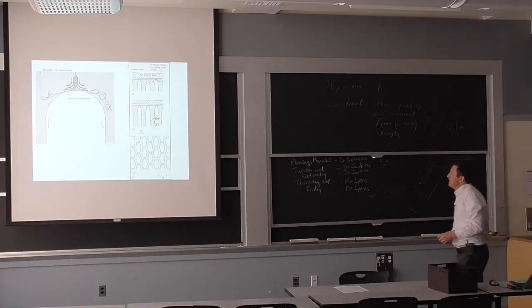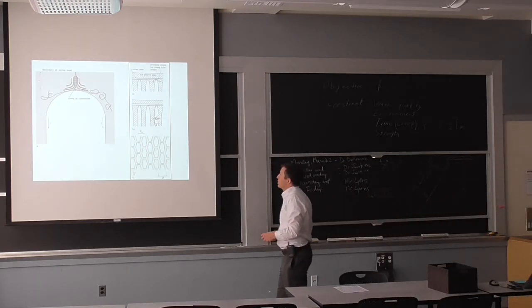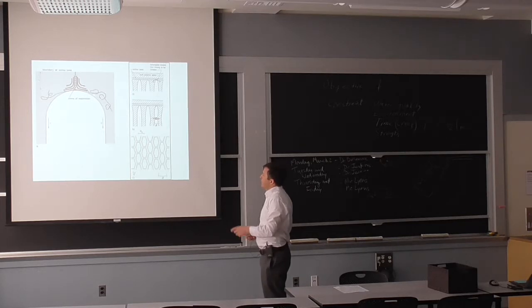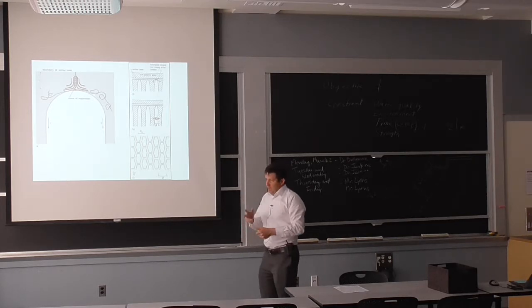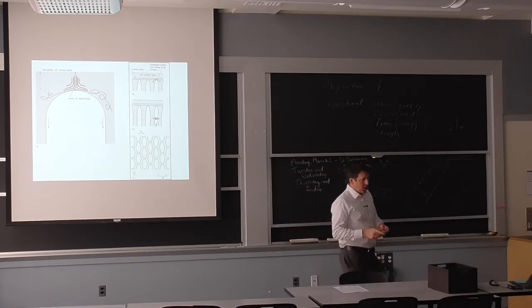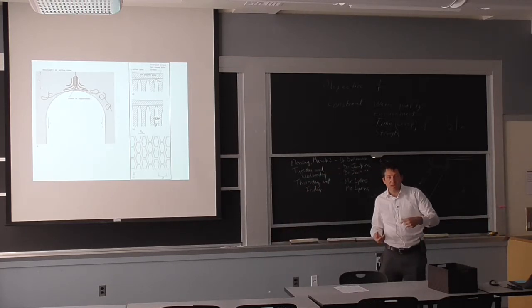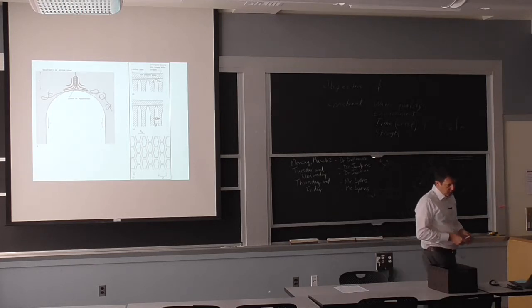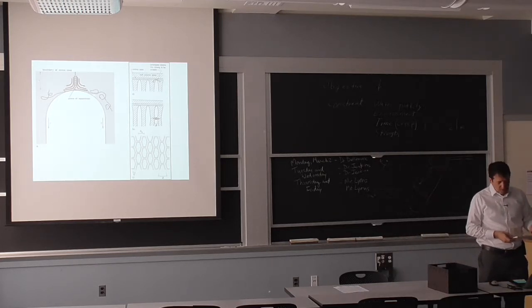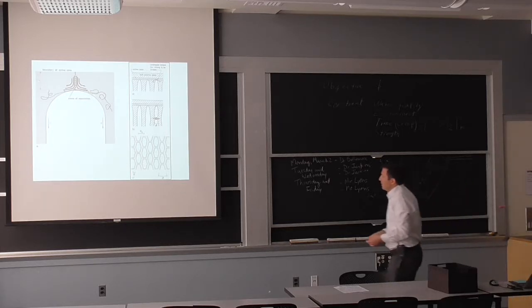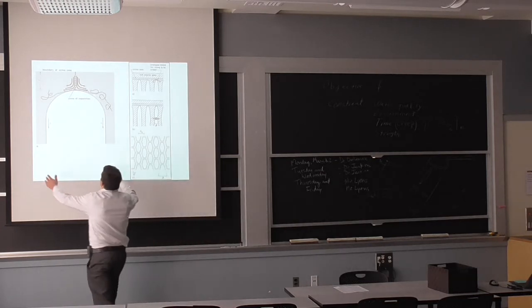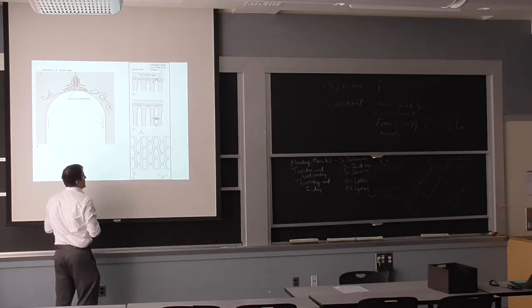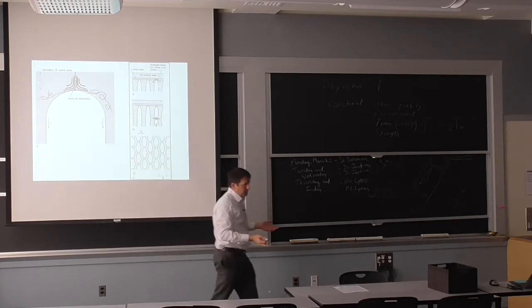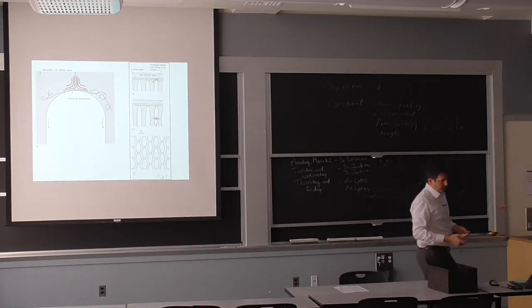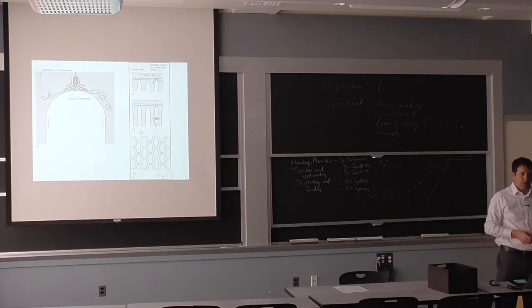A little bit more in detail here on how the craze can grow. Again, it is not by section of each chain. It's one chain is going to have to go on one side or the other side of the crack front. And that's a slow process, but it can be pretty quick if you don't have a lot of molecular weight. So if I'm thinking of chains that are, say, 50 micrometers, and that's the overall span of where the molecule is going, it can move around very quickly. But if the chain is very long, then you don't have that problem.